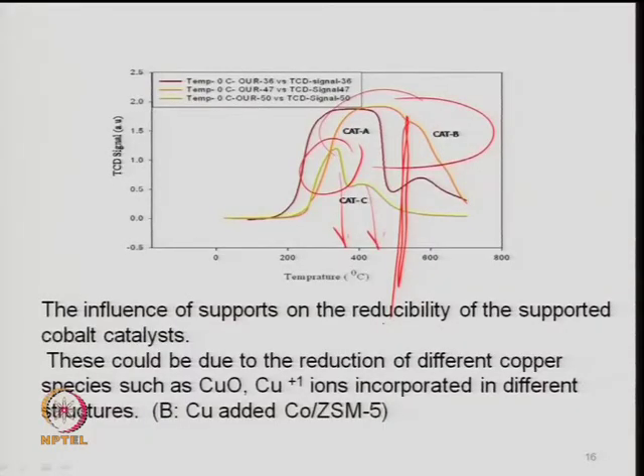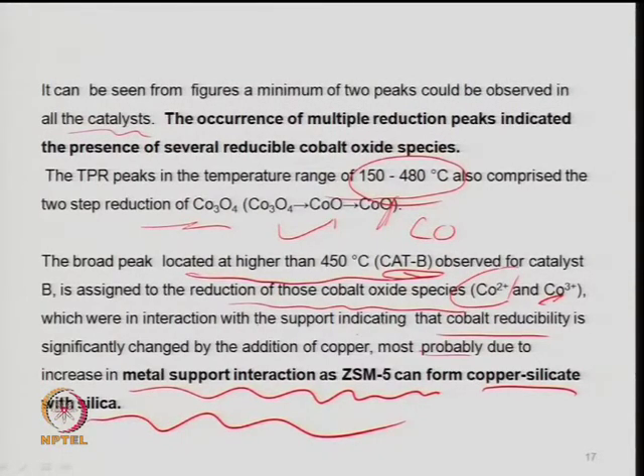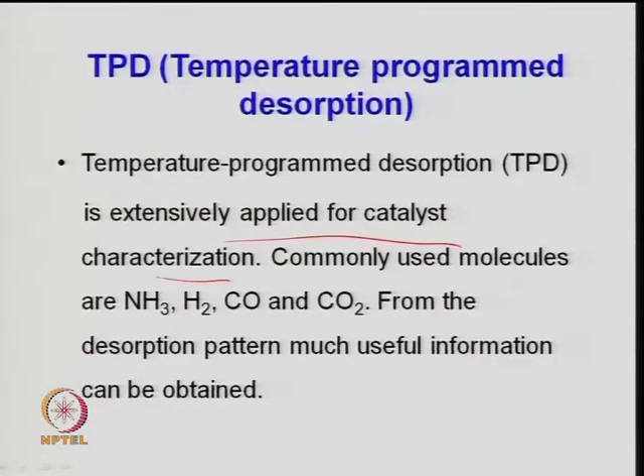TPR gives useful information on reducibility and can indicate metal-support interaction at least qualitatively. Temperature Programmed Desorption (TPD) is another important tool to get active sites or acidity and basicity of the catalyst. Ammonia, being a basic gas, reveals acidic sites. Carbon monoxide can also be used for active site determination and to study desorption kinetics. Carbon dioxide, being an acidic gas, reveals the basic sites of the catalyst. Pyridine or any basic gas can be used to find acidity, and Lewis-type or Brønsted-type acidity can be calculated.